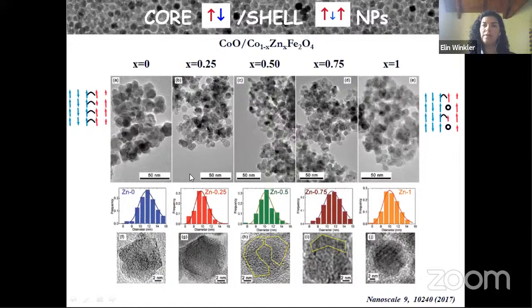When we do it in that way, we have the advantage that the systems present a very similar size. All the nanoparticle sizes are approximately 10 nanometers. As you can see, these are the size histograms. And here you can observe some high resolution TEM images where you can see the core-shell structure. In some cases, you can observe the crystalline planes.